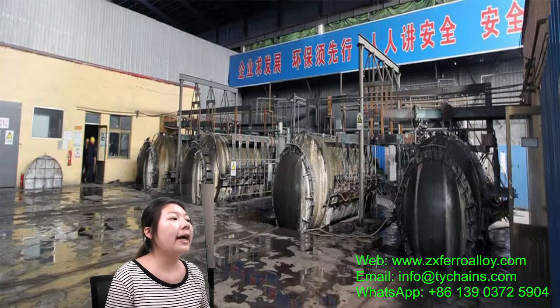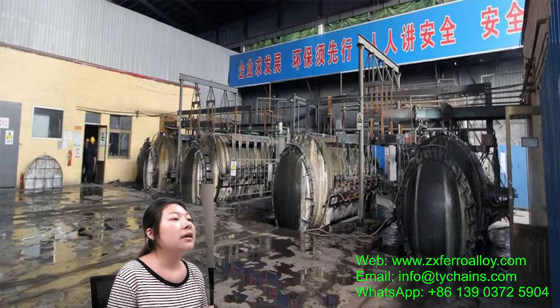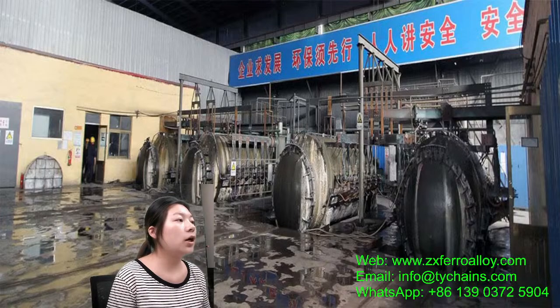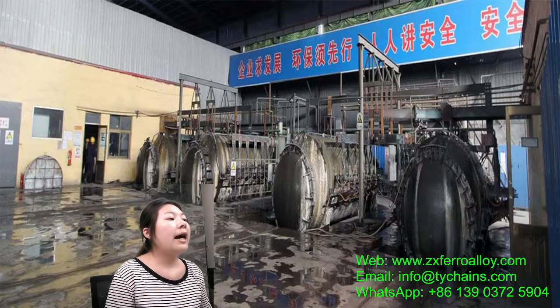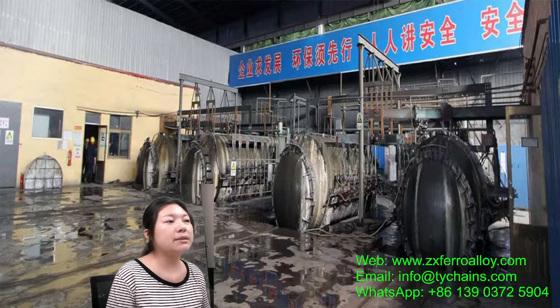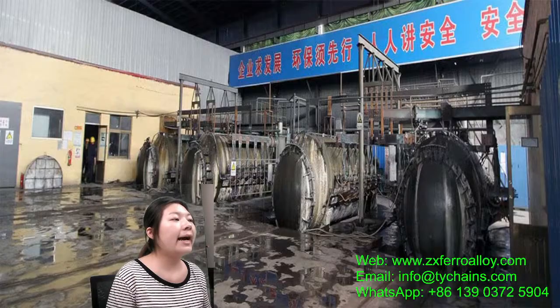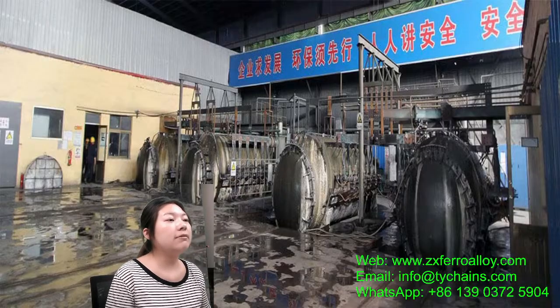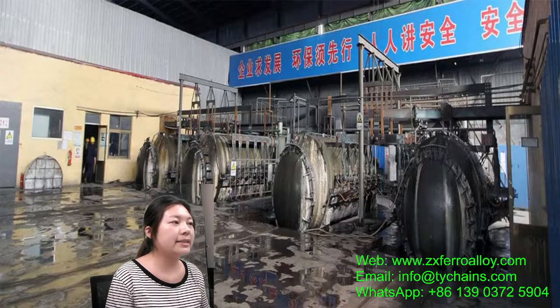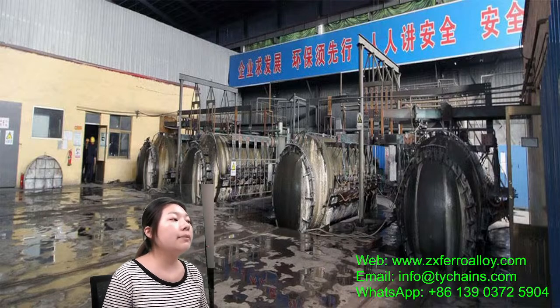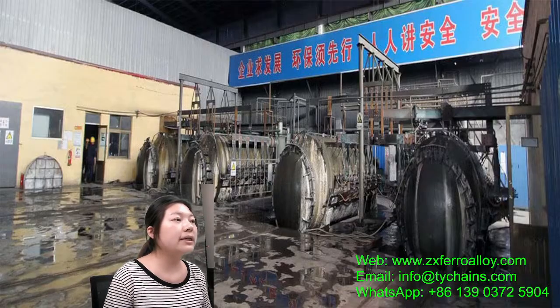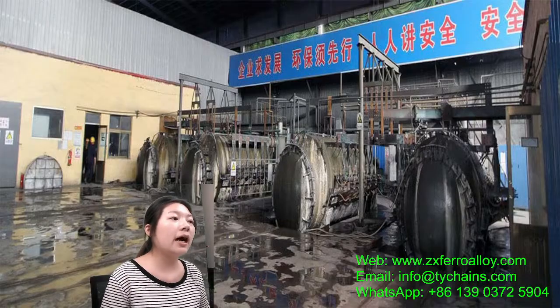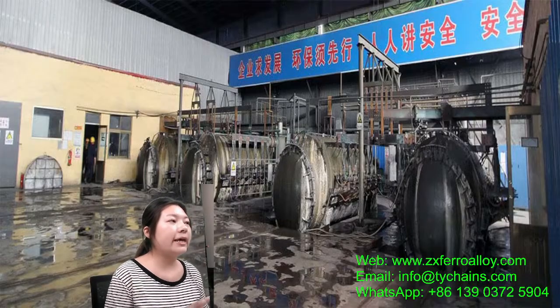Calcium alloy cored wire can replace calcium silicon cored wire and calcium aluminum cored wire to process copper steel taps, and the calcium recovery rate can be increased by more than 52%. The use of the calcium cored wire can effectively reduce production cost. The feed weight of the pre-cored wire per ton of steel is only about 38% of the calcium silicon cored wire. So our company cored wire is tightly wound and wrapped tightly, supporting long-term strength.